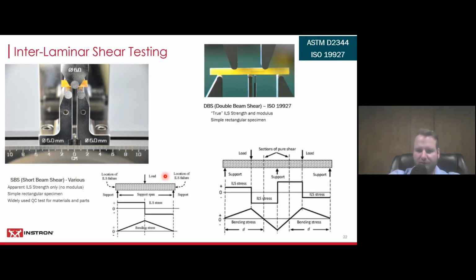For that, you would need something like double beam shear, which is ISO 19927, where you can use a LVDT or a plunger down here to determine the deflection. It will give you true interlaminar shear strength, and you can determine the interlaminar shear modulus as well. You can see the failure right here on the side in between the specimen. So that's how interlaminar shear testing looks.